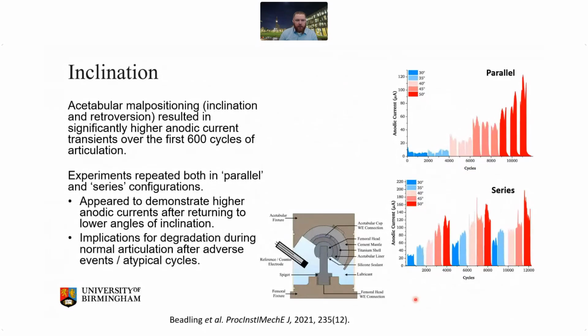Again, no surprise, increasing inclination resulted in increases in the corrosion current that we were measuring. But what was interesting was that when I changed how you increase the level of inclination from 30 to 50 degrees, whether you ran them in parallel or in series, when you come back down to 30 degrees after a high level of inclination, the corrosion currents were higher at that 30-degree angle than previously.